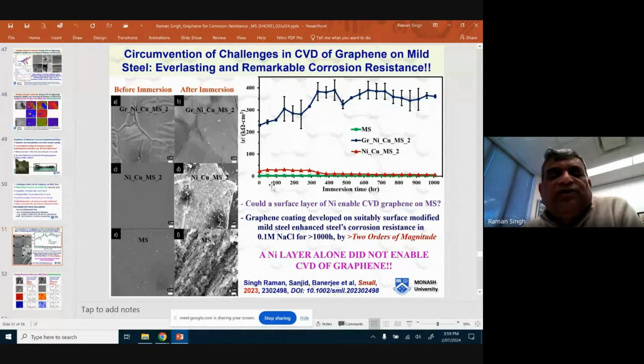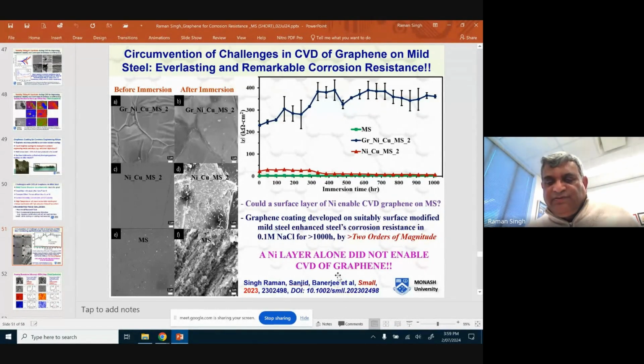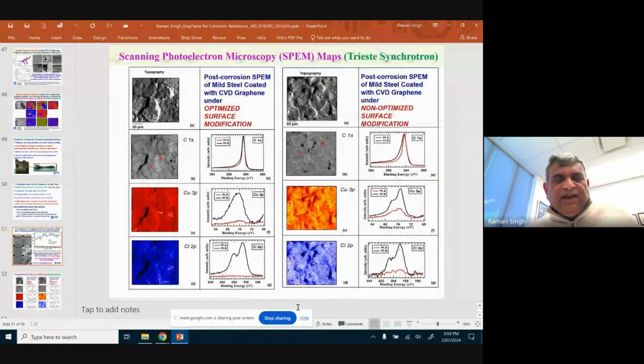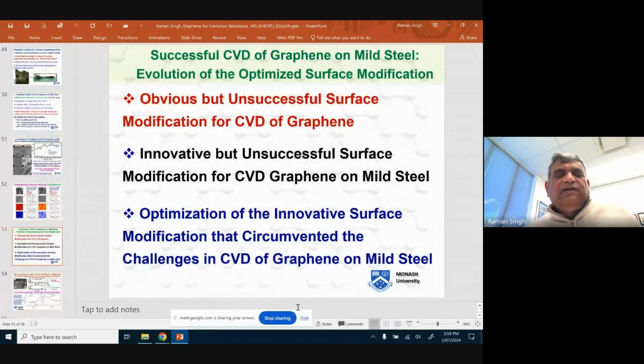It does not react. It does not allow penetration by corrosives. And we had 2 orders of magnitude improvement. Again, you can see that the graphene coated mild steel, after immersion for 1,000 hours, shows no change, whereas mild steel as such would be corroding very fast. And as I said, this work was published last year. So, how did we achieve this?